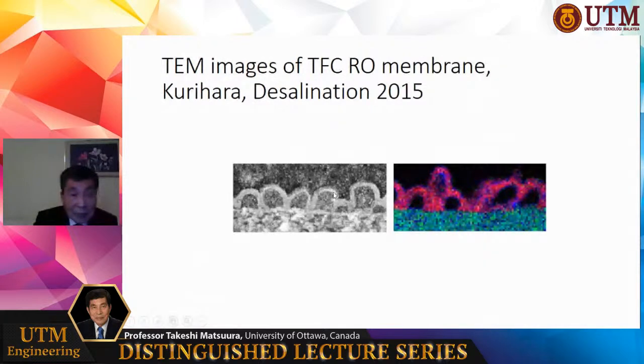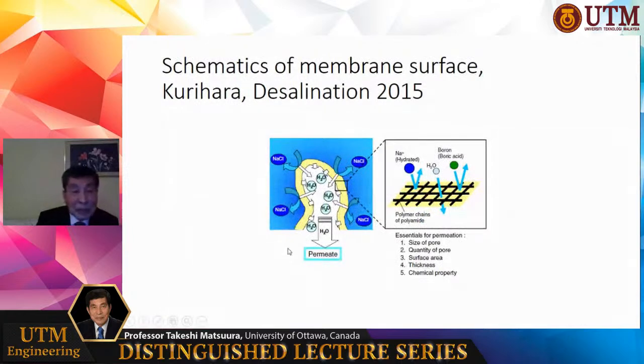So this is the reason why it has very high productivity, because the surface area is not this, but the area is like this. So surface area is expanded very much by this structure. So this is the reason why this TFC membrane has a superior performance. Or you can see that this is a void space filled with water, and this is a thin layer. Sodium chloride is rejected, only water flows through this polymer layer. And this is the detailed image of the membrane.